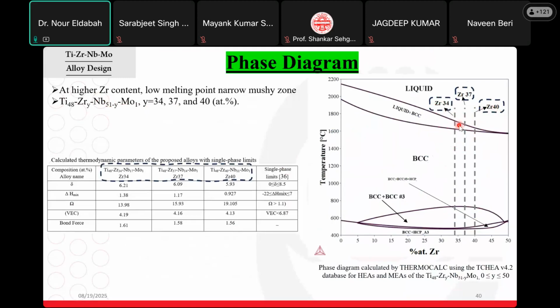Also, a low mushy zone. A low mushy zone will reduce the segregation inside our alloys, and the columnar and dendritic structure. So you will reduce the segregation in your alloy. This is the region of BCC, and as you know, the machine learning and the classical design rule recommend the existence of the BCC beta phase.